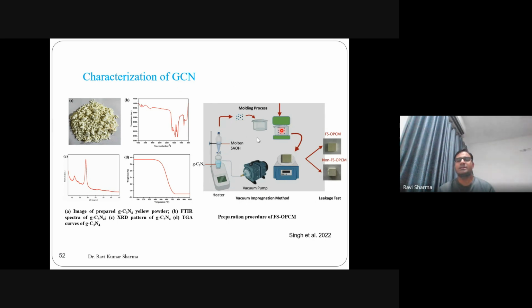This was the process we followed, called the vacuum impregnation method. In this method, vacuum is created into the beaker, and then the GCN, graphitic carbon nitride, was added in small parts into the liquid PCM, and it was rigorously stirred and left to stand for about 1.5 to 2 hours. After stirring, it was allowed to solidify.